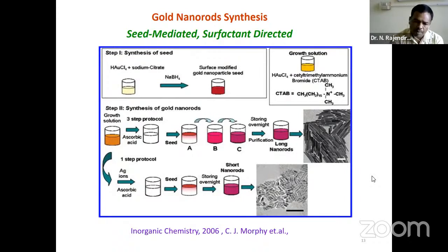So in the year 2006, C.J. Murphy used a seed-mediated approach for the synthesis of anisotropic particles, for which he prepared two solutions. This one is the first step: he prepared a seed solution. And the second step is the growth solution. In the seed solution, he used the respective salts. Here he used auric chloride, sodium citrate, that is a stabilizing agent, and added sodium borohydride, that is a strong reducing reagent, and he prepared seed solutions.